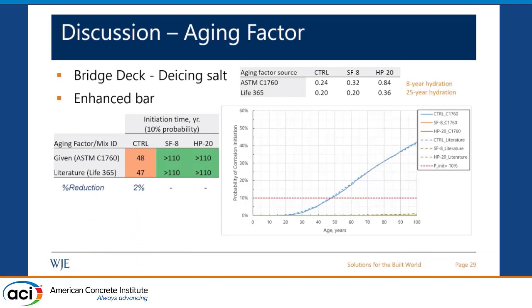Looking at the enhanced bar cases, the aging factor was not as significant with predicted service life as the cases of black bars, especially for the mixes with silica fume and natural pozzolan. I ran the analysis up to 110 years, so I didn't extend it further. It could have resulted in bigger differences if we extended the analysis period.